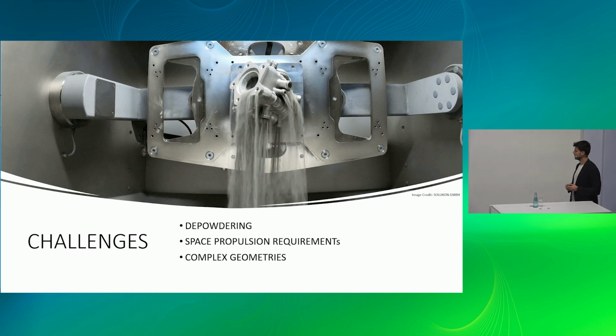So complex products have a lot of challenges, and that's also the case here. One of the biggest challenges is in depowdering. So you can imagine if you take out your part and it's completely filled with metal powder, all the intricate structures, all the cooling channels and the cavities are full of powder, obviously. So how do you get that powder out? Just by using a vacuum does not work because the density of these Inconel powders is too high. You can actually not remove a lot.